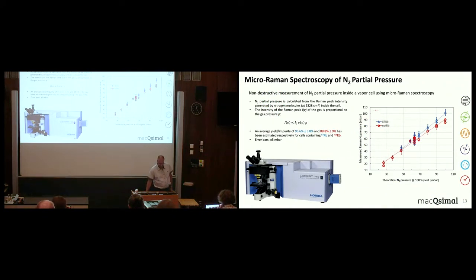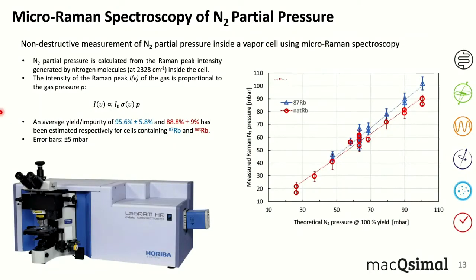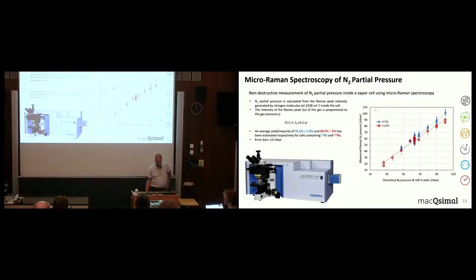And so from this measurement, you get a Raman peak intensity, which is generated by the nitrogen molecule. And this peak intensity is linear with the intensity of the laser, with the Raman cross-section, and with the pressure. With this method, we always do this on some cells per wafer to have a quality control. We were able to measure the yield and the purity of the azide.